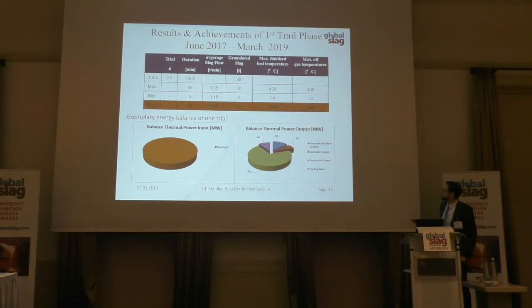The small part, the violet part, is the cooling water. As I said before, we are impacting with very hot slag onto water-cooled balls, so we extract a lot of energy there. The blue part: we are operating this plant batch-wise, so we're starting in cold conditions, and the granulate bed starts at, let's say, 50 degrees. After the end of the trial, we have 400 degrees. So this part is the energy we need to heat up the granulate bed, and the red part is the energy that's still in the granulate when we discharge it. So we have a temperature of up to 500 degrees at the discharge.